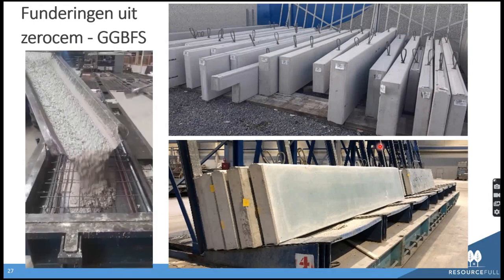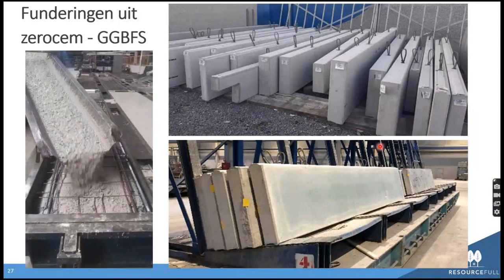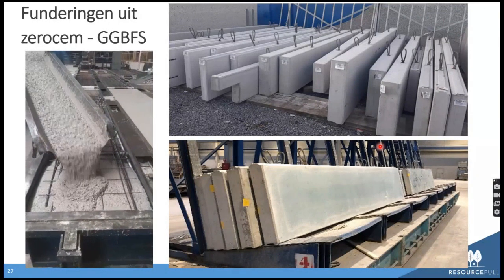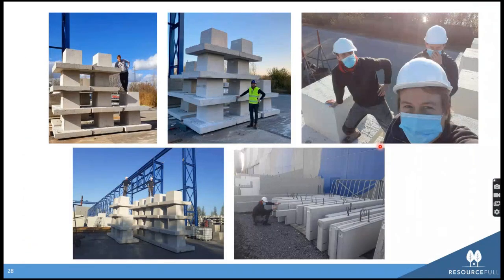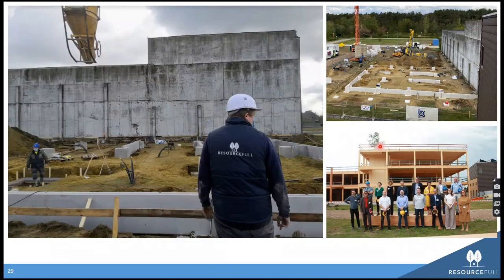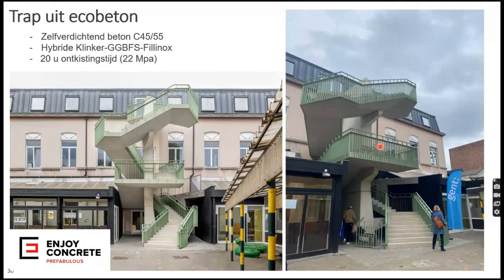This was then further fine-tuned into a self-compacting geopolymer, add water only, where we produced, I think, 120 cubic meters of blast furnace slag activated, which we put as the foundations in a new building, and we are now monitoring the quality over time. Here was the first time ever we really built something structural. This was this hybrid concrete, something Niki also implemented in TBI, I believe, in Voorbij Prefab, the time he was working in ABT, very similar mix, where we can reduce the amount of clinker to a very low amount, but still have a demolding time of 16 hours, 20 hours, okay to turn in prefab companies.